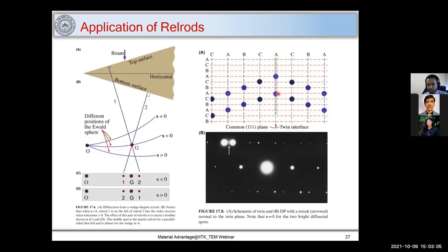So let's consider a twin. You must be knowing twins, and let's consider this as a twin interface. So here in this case, let me mark here. The rel rods will be in this direction, and you can see that there will be streaking occurring. Because of the Ewald sphere, let us mark an Ewald sphere. When the Ewald sphere passes through like this, it will cause streaking in this direction. And that is why we see two spots also because of these regions. So even though there is twinning, we see these two twin spots. And that is a mark that there is twinning in the material. So you have streaking because of this small plane, which is there as a twin interface, that causes streaking. And you have this orientation change, which causes twin spots here.